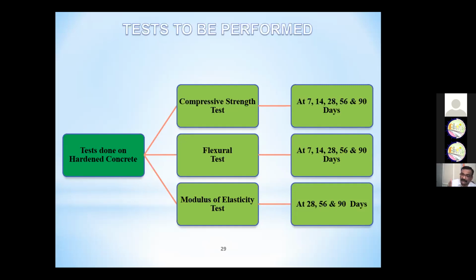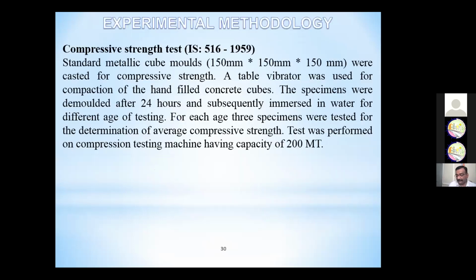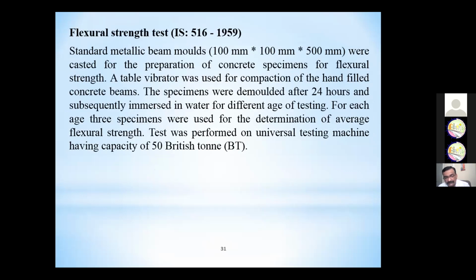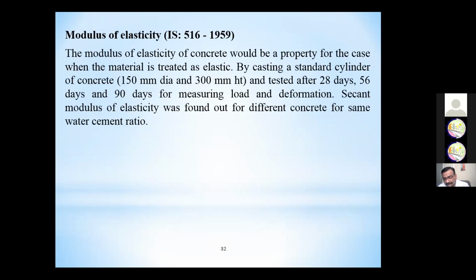Fly ash gains strength during the period of time. If you give it duration, the strength increases in fly ash, as per Malhotra, the Canadian researcher. Now the standard experimental methodology for compressive strength is as per IS 516:1959. We will not go into this experimental methodology because we all know the compressive strength test. Then the flexural strength test is as per IS 516:1959. Then for modulus of elasticity, we require a cylinder of 150 mm diameter by 300 mm, at different ages: 28, 56, and 90 days. We measured the load and deformation.